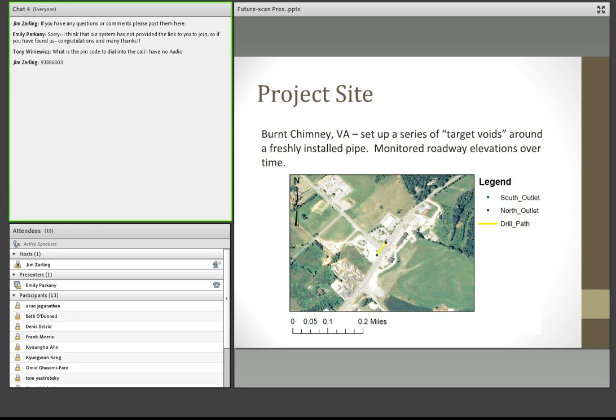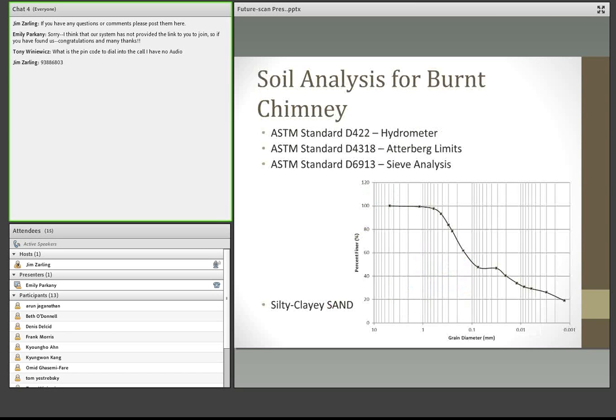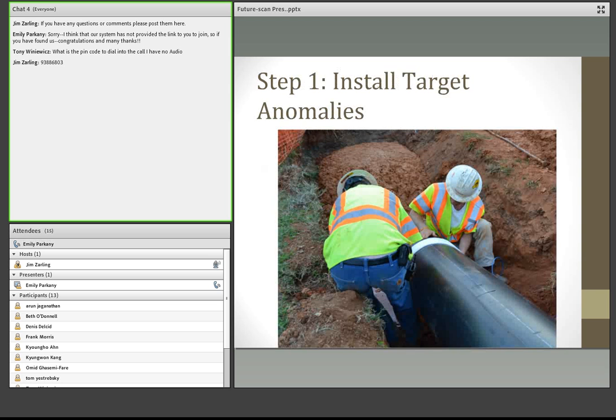Also during the study, we did a series of roadway elevations, and we monitored those over time. We did one set of elevations before reaming occurred, one during reaming, one immediately after installation of the pipe, and then one about 4 months after the pipe had been installed. All right, so we also did soil analysis at the site, just so that you can see exactly what kind of soil we were working with. We did most of the standard tests, and had a USDA classification of a silty sand. So that lets you know what we're working with.